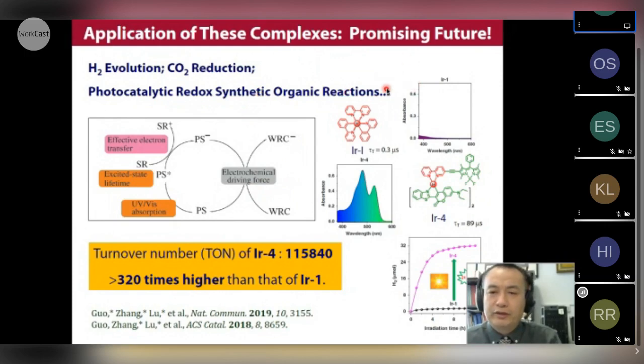The last point is that the application of this kind of new complexes is just at the beginning. The future will be promising because some researchers studied the application of these complexes in hydrogen evolution. And we can see with the new complexes, the hydrogen evolution rate constant is much larger than the normal complexes. I think this one is still used in photocatalysis, but actually you have a much better solution. You can use the new complexes showing strong absorption of visible light and a long lifetime. So you will get a much larger turnover number or turnover frequency for the photocatalysis. So I think in this case, both the supervisors and the students will be happy because you can have very good data and you can have very good publication.